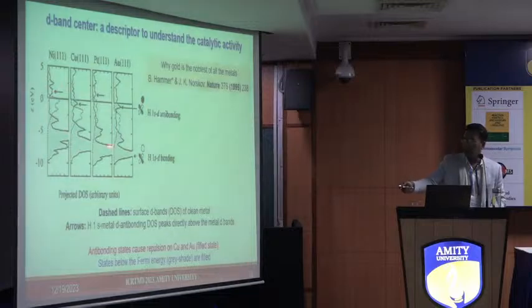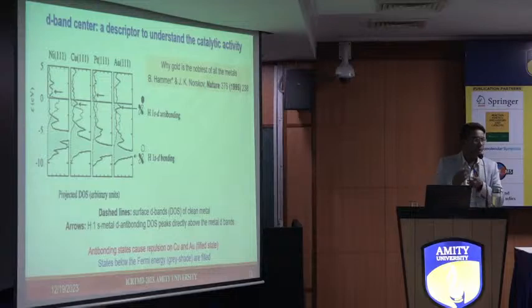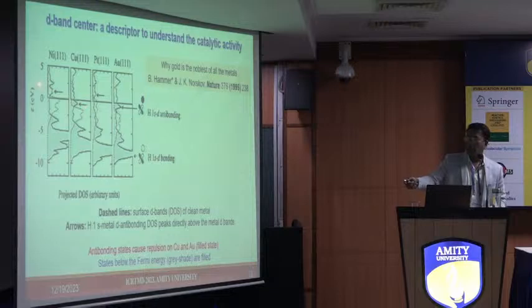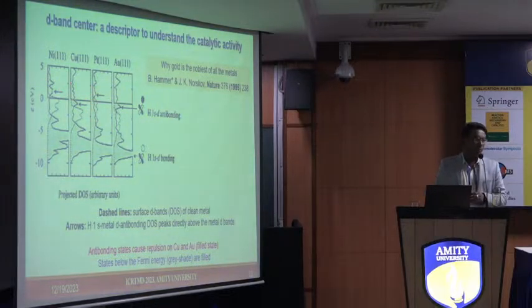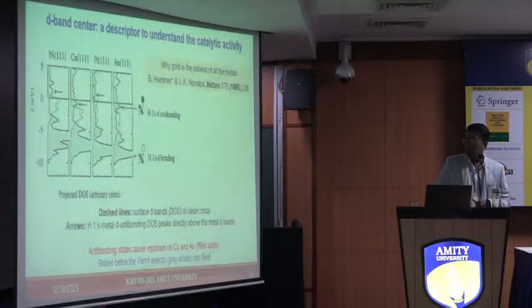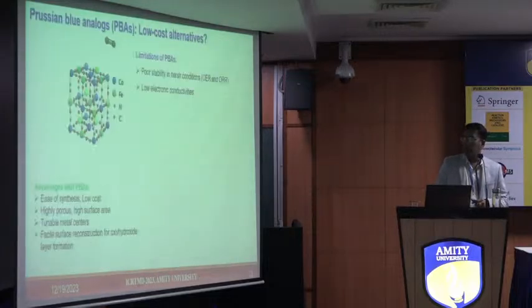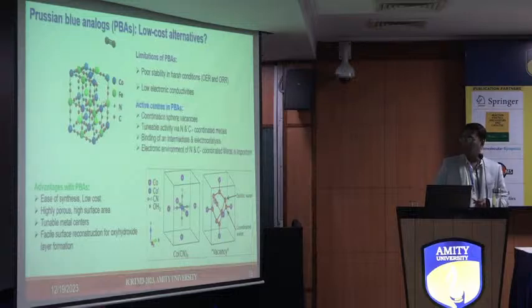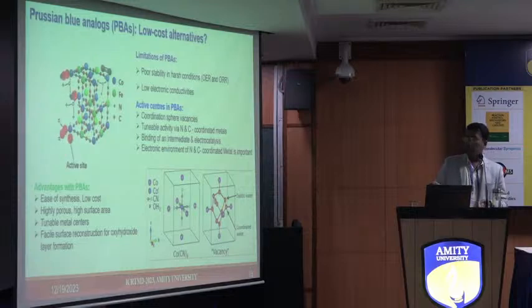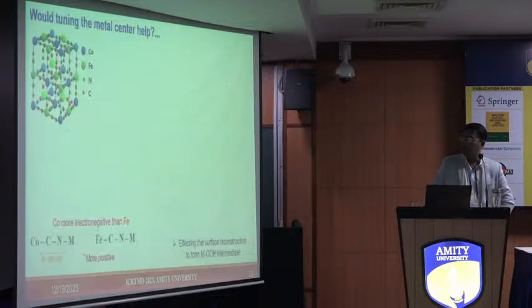As the d band center is moving, the number of vacant orbitals above the Fermi level are changing. The higher the number of vacant orbitals, the stronger is the bonding of the adsorbate on the surface. Okay? So what you need is the optimum number of vacant orbitals above the Fermi level. And that is what we tried to do for this application. For example, we took these Prussian blue analogs, and due to lack of time, I'm not going into much of the details, but I'll go to what exactly we have done.